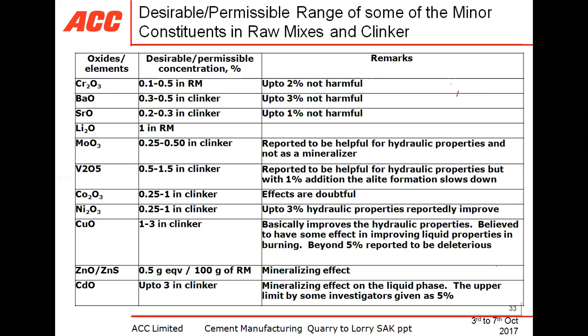If these elements are present up to a certain percent, there is no harm in this. But when it exceeds the level, then it becomes problematic for our clinker quality or cement quality. For example, chromium, if it is present up to 2% in clinker, it is not that important. But if it exceeds and comes into cement, then it becomes problematic, because chromium is highly dangerous for human skin. When a mason comes into contact with cement that has a high amount of chromium, they will get some rashes on their skin, or it causes eczema.